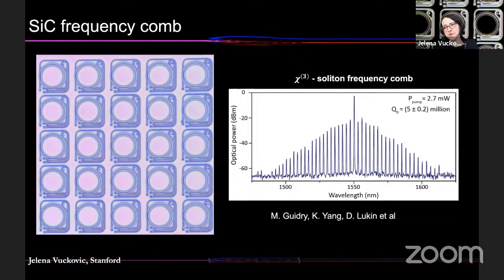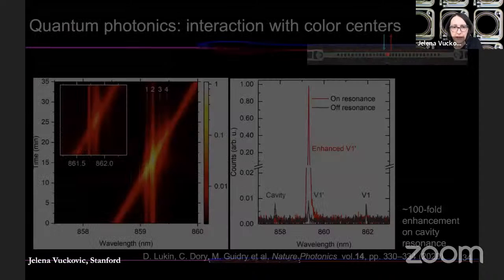This on its own has a lot of interesting potential application in metrology, but also in quantum photonics that doesn't even involve quantum emitters. But I am showing it here, although our primary interest is in using optically interfaced spin qubits. I'm showing this because it tells you that the quality of photonics is extremely good, and that you can actually use this platform also to do quantum frequency conversion right away, right? If you would like to interface your emitter to fiber optic network, you don't need additional materials. You can do everything inside of silicon carbide, converted from 900 nanometers to 1.5 microns.